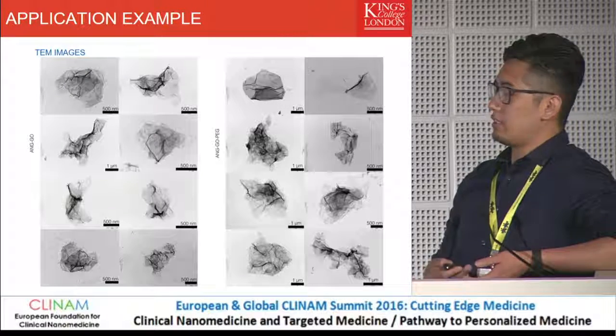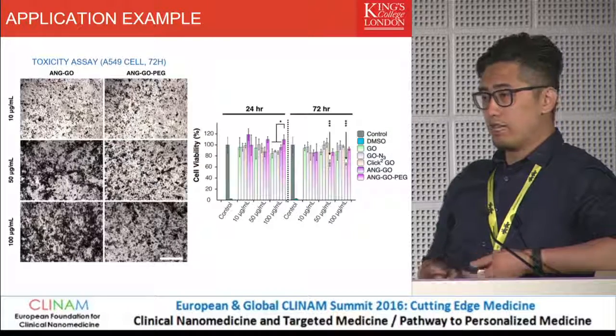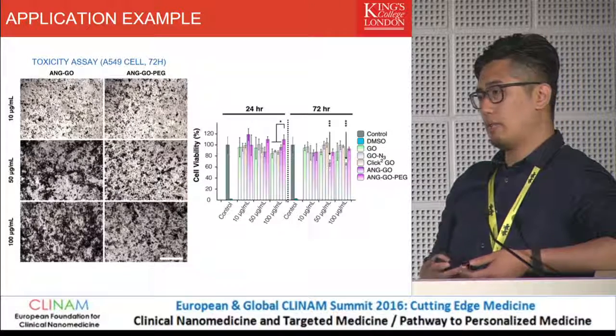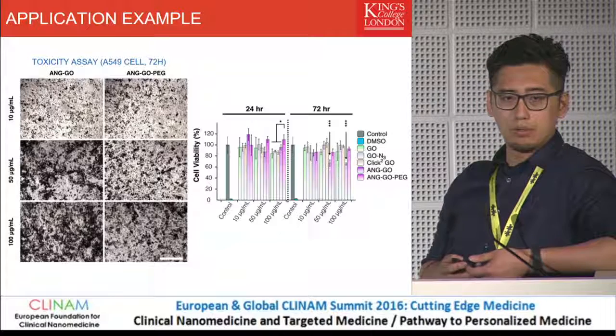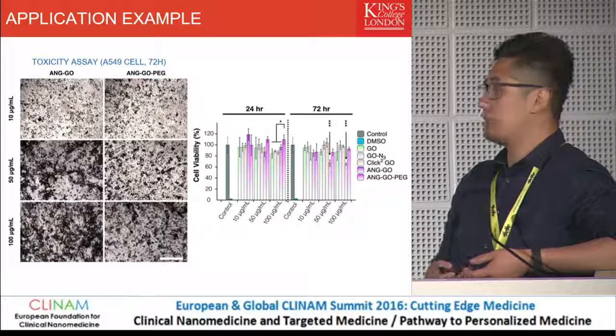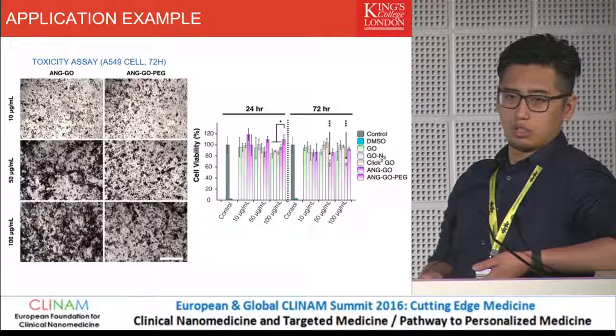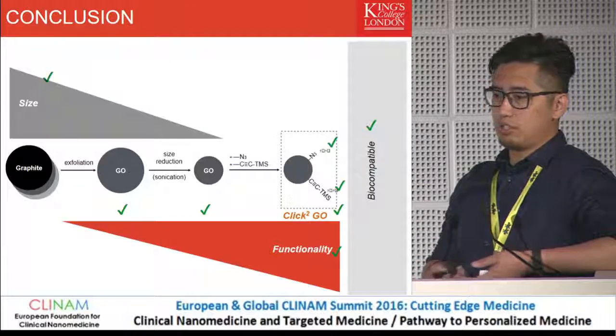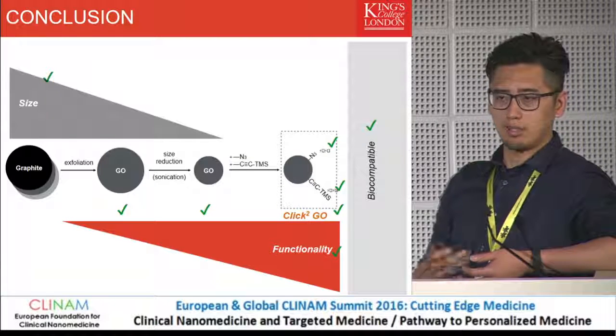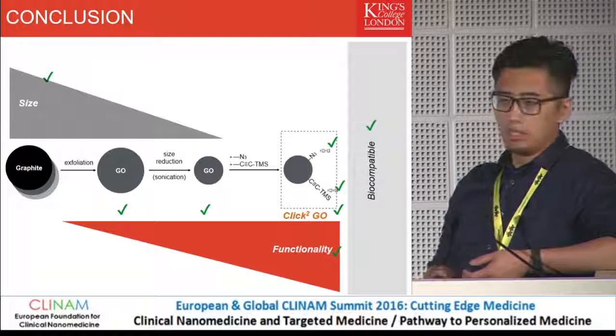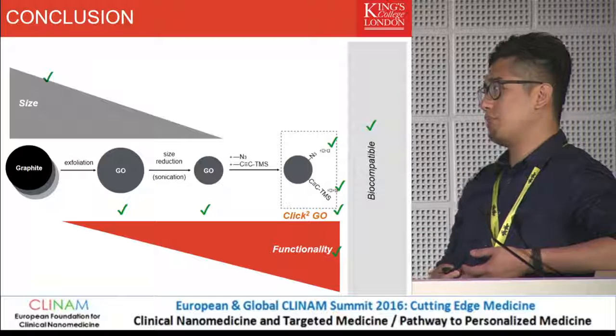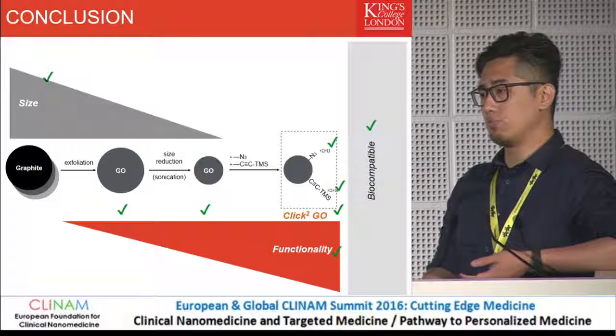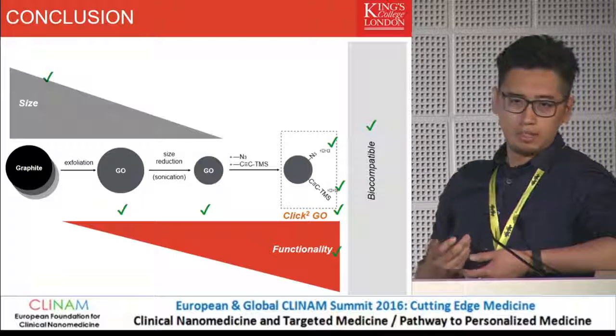This is how they look after the click reaction — they still behave like graphene. We tested on A549 cells at three concentrations, and we only found toxicity on the graphene with the peptide click at higher concentration at 72 hours. This is most likely because the peptide is cationic, causing toxicity to the cells. But because we also do PEGylation, which kind of shields the peptide, we reverse the cell viabilities in the end.